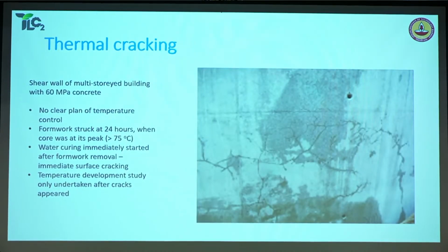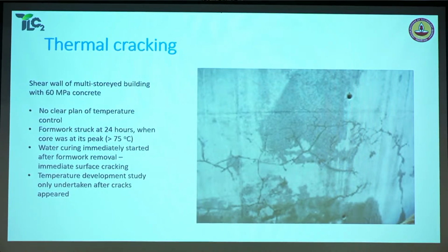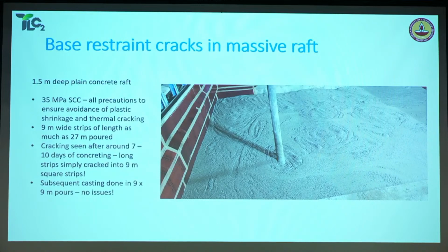Same image here. And of course, after the cracks appeared, they started doing temperature monitoring, and then they started placing requirements for temperature control of the concrete. This was again another project in which a plain concrete raft was done with 35 MPa self-compacting concrete. All precautions were taken to ensure that plastic shrinkage cracking could be avoided.